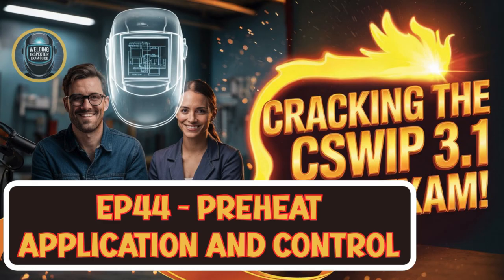Hydrogen in the weld. Wow, okay, that sounds like a really serious unseen threat. How does preheating actually help with that specifically? And are there other benefits too? Oh, it's a huge threat. And preheat gives you several crucial advantages to stop those defects and make sure the weld is strong long term. Firstly, it slows down the cooling rate, both of the weld itself and also the area right next to it, what we call the heat affected zone, or HAZ. That's the base metal that didn't melt, but its structure got changed by the heat.